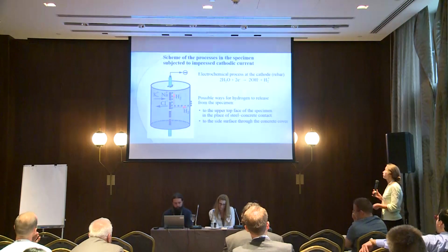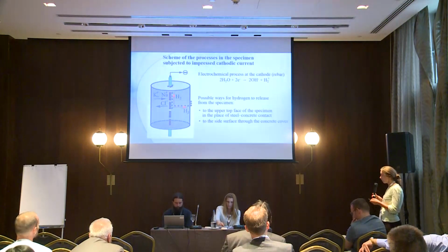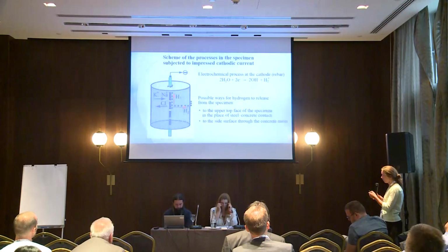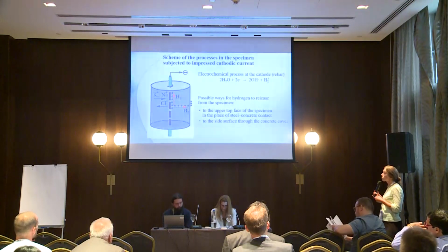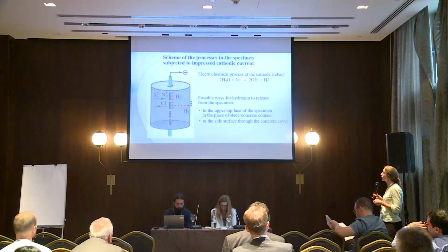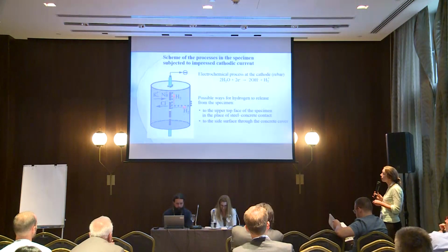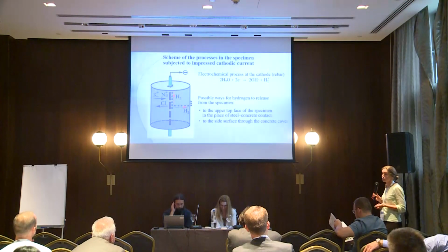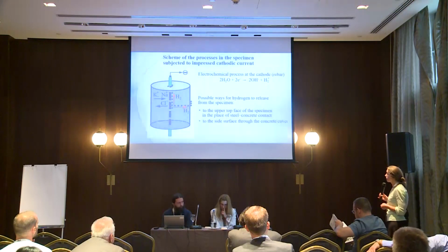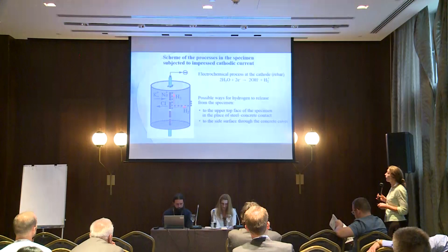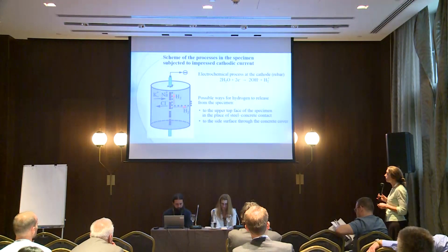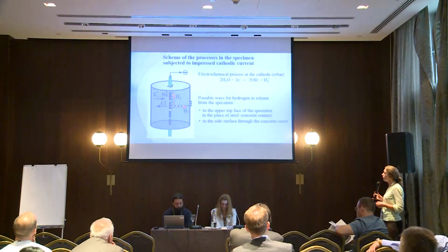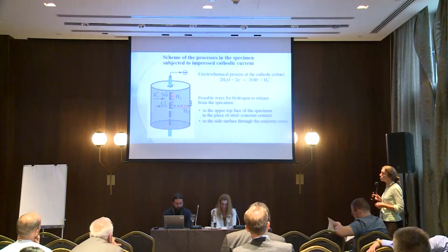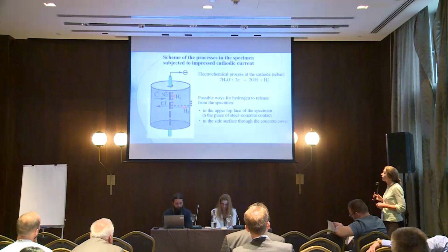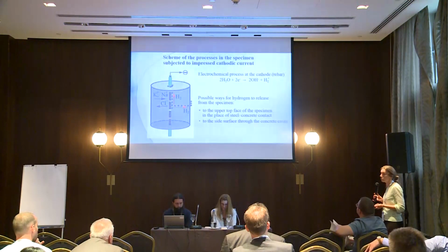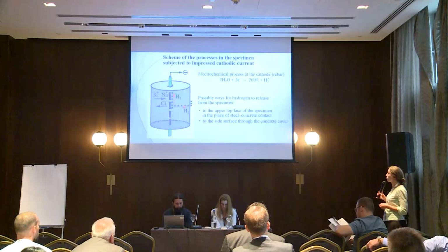It should be noted that during cathodic polarization, chloride ions move from the reinforcement, while potassium and sodium ions move toward the reinforcement. It is the phenomenon of electromigration. And it has been shown by several researchers that rising concentration of these cations near the interface leads to softening of concrete paste. So under such conditions, we should expect loss of bearing capacity of reinforced concrete.